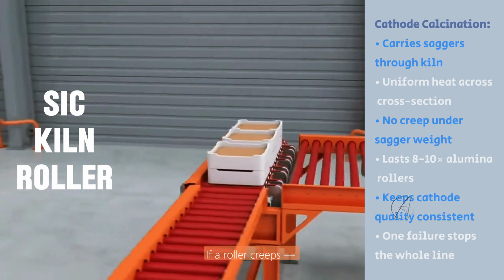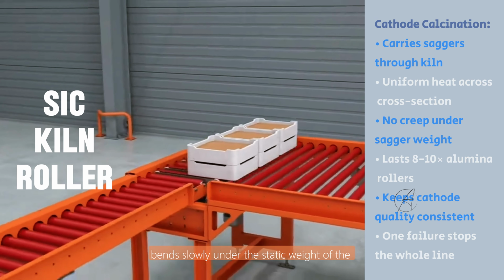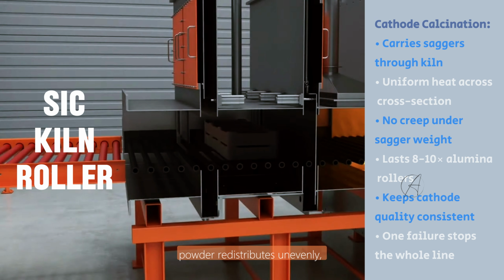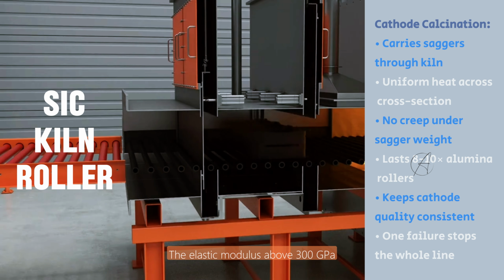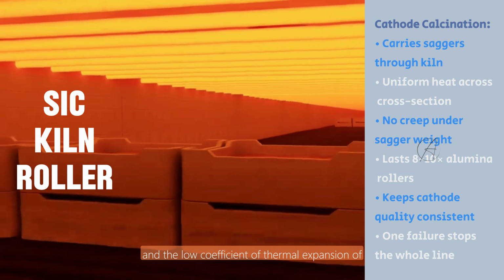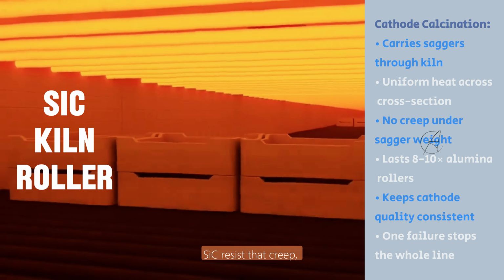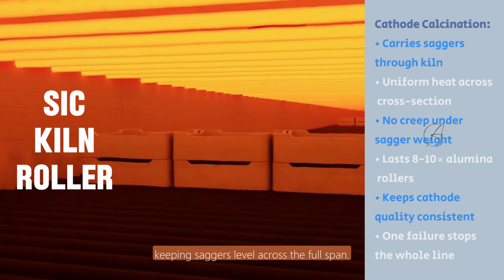If a roller creeps, bends slowly under the static weight of the saggers at high temperature, the saggers tilt, powder redistributes unevenly, and the calcination quality of that batch is compromised. The elastic modulus above 300 gigapascals and the low coefficient of thermal expansion of silicon carbide resist that creep, keeping saggers level across the full span.